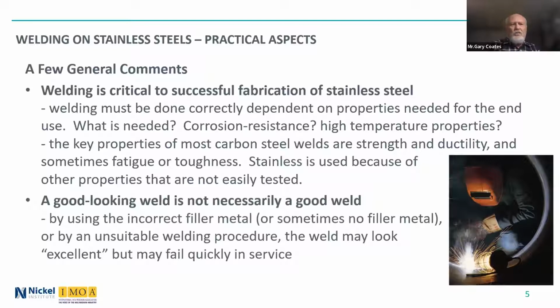So one of the things that welders often say when they're showing off a weld is, this is a good looking weld. And that is important, but it's not necessarily a good weld if they've used the incorrect filler metal, or sometimes no filler metal where filler metal is actually needed, or they used an unsuitable welding procedure, too high heat input, for example. The weld may look good, but it may fail quickly in service. And of course, they do not see that.